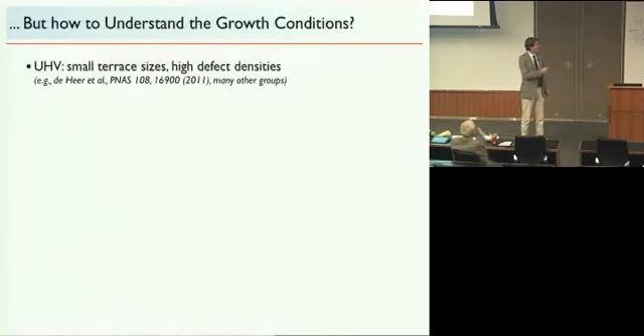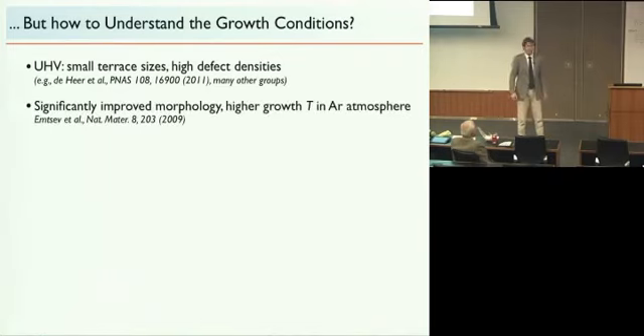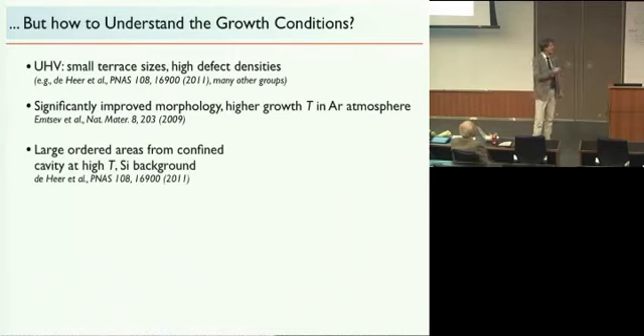Again, we want to grow it. And I already told you that if you just grow this in ultra-high vacuum, you end up with pretty inferior quality films. That's well established in the entire community. And in fact, in 2009, a partial solution to this problem came along from a group in Erlangen around Thomas Seyller and co-workers that showed that you could significantly improve the growth morphology if you grew at a higher temperature in an argon atmosphere, so not in vacuum. And then there's the De Heer group, who have used their cavity growth recipe that they published in 2011 for a long time in a silicon background. Also, temperature and pressure play a role.